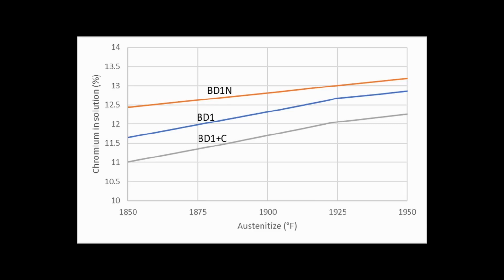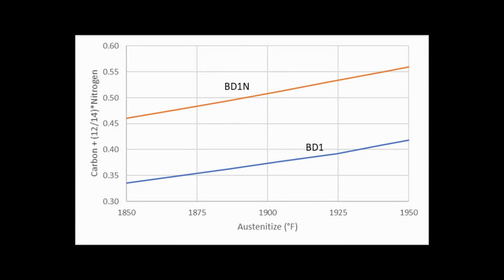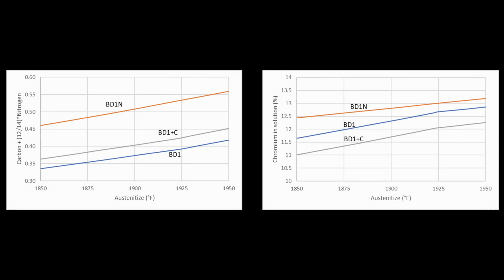Yeah, using that software, it really hits home here because, from that first graph you had there, you could see by adding the nitrogen to the BD1N, you have that much more carbon and nitrogen in solution, which is increasing hardness. So then you're like, well, why don't you just put more carbon in there to equal that out? And then these next graphs you show using that software, it's really exciting because you could see even if you added the same amount of carbon to equal out the BD1N, the nitrogen, it doesn't increase how much is in solution, and then it drops chromium in solution. So it's like, oh my goodness, look at that.